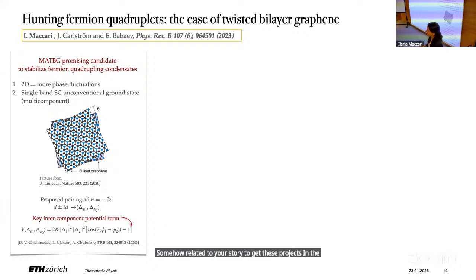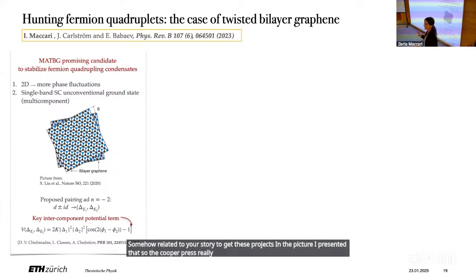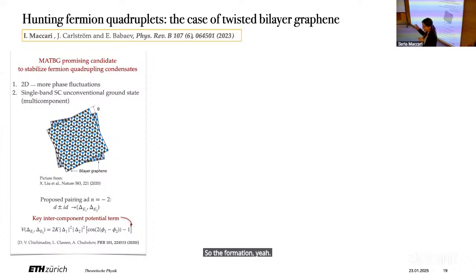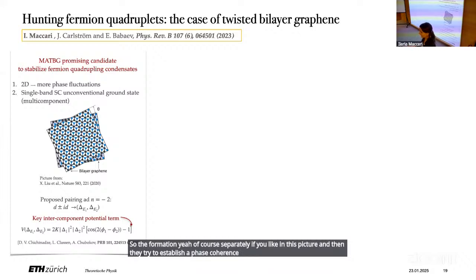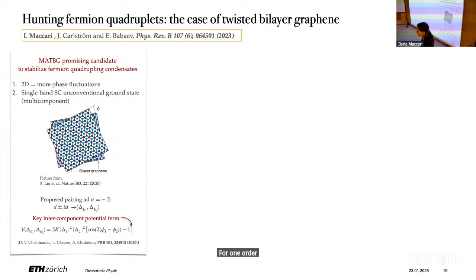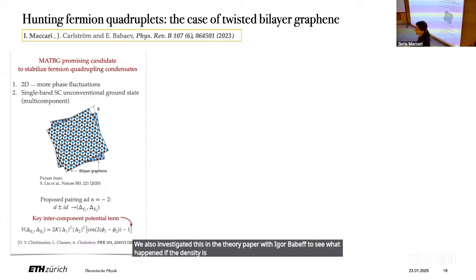In the picture I presented, the Cooper pairs really form and belong to different bands, and then they interact with each other. So the formation happens separately, if you like, and then they try to establish a phase coherence overall. And this is done via this interaction that can be Josephson-like or the standard. But there is no need for one order parameter to be strong. No, not necessary. We also investigated this in the theory paper with Egor Babaev, to see what happens if the density is different, but qualitatively it doesn't change.